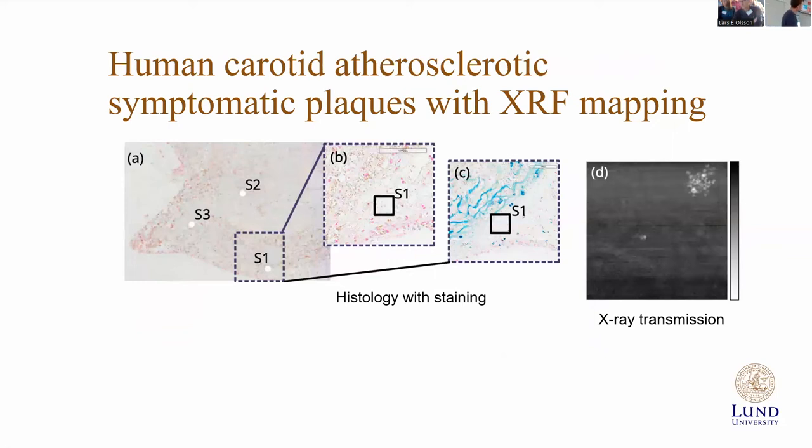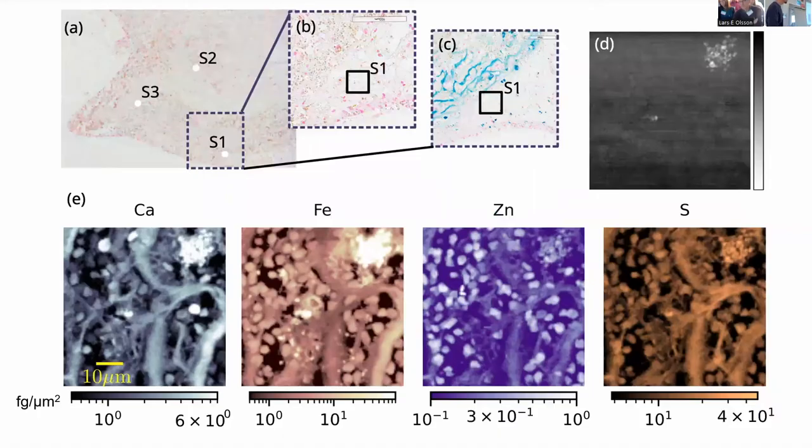So here is again the same sample as before, the carotid plaque, and after we have done the sectioning and histology, we can identify regions that we want to look at with high resolution X-ray fluorescence microscopy. And then we can map out. So here's one particular region, the S1 region. And we see the image up here to the right, that's the X-ray transmission. So we see there's something that will show up in the microCT image as a calcification. These are some absorbing structures, and they are, sure enough, mostly calcium, but also a lot of iron, you can see. And we can see the distribution of zinc and sulfur and other elements that are there